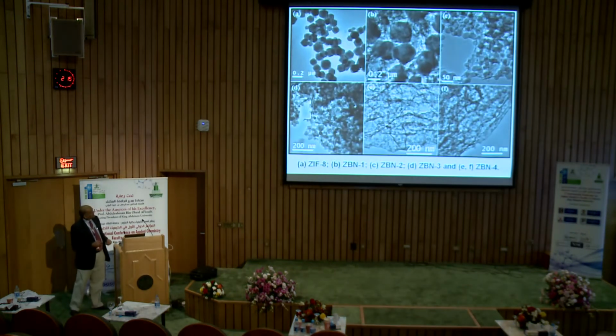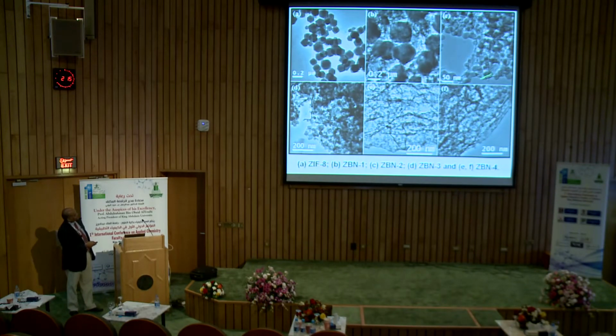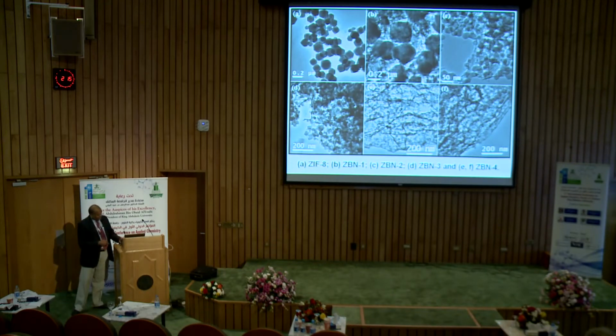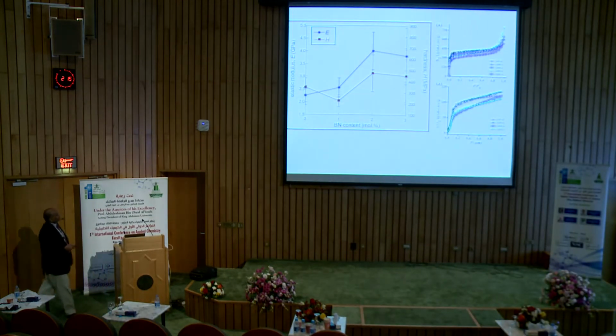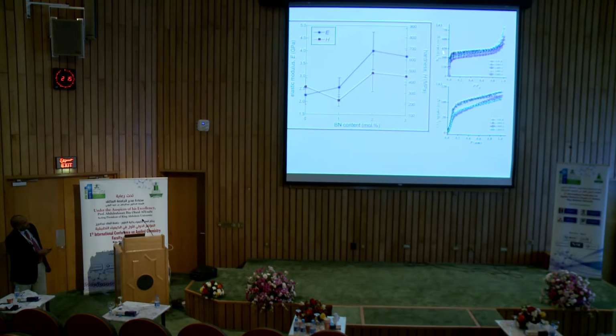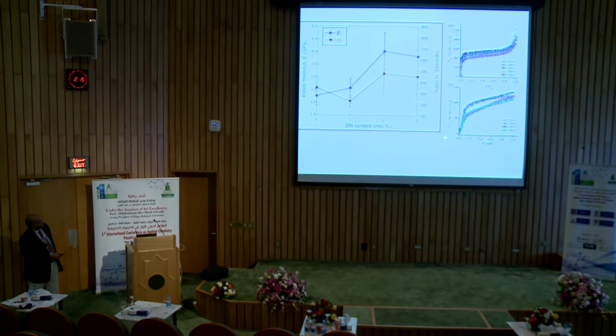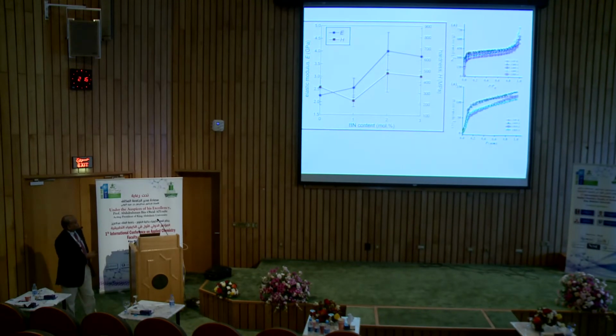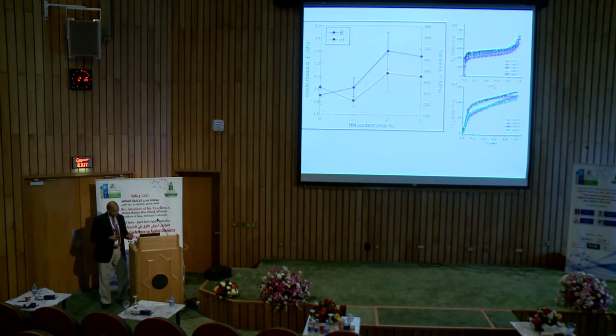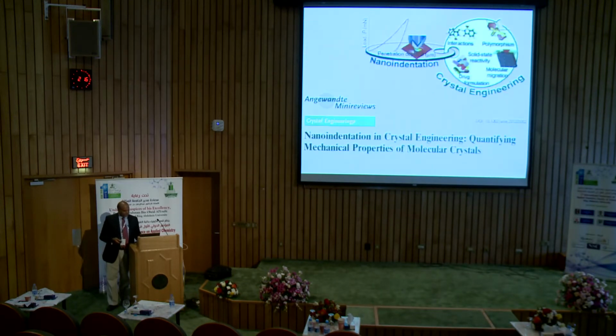It's a schematic, and these are the kinds of things. This is ZIF-8 alone, but here you could see this boron nitride sheet and ZIF-8 particles. So we made these kinds of composites, and again, what we'll see, the functionality, this is uptake of nitrogen or carbon dioxide. The functionality is not lost. You get the same functionality, but at the same time, as you increase the boron nitride content, you could have pretty dramatic improvement in mechanical properties. So these are ways one can actually achieve mechanical integrity while your functionality is preserved, and this is possible. To measure those kinds of things, you can check it out with the nano indentation technique.